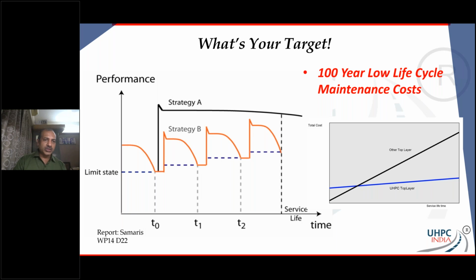On the left figure, you see something in orange, where you build a new structure, over time it deteriorates, you repair it, and then again it deteriorates. The same cycle goes on, and you keep pouring money onto it until 100 years. But with UHPC, if you once use UHPC, that's what Strategy A is in black. If you use UHPC, it's good for the entire service life. You don't have to do anything to your structure with UHPC. So the right side pretty much shows that over the life cycle of your project, there is a huge savings. Now imagine what India as a country can save when we use UHPC in the long term.